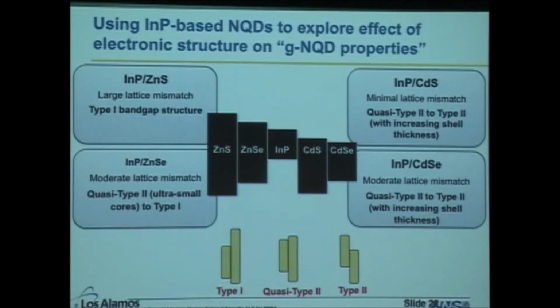And we like indium phosphide in general because if we tweak the composition of the shell from zinc sulfide to zinc selenide to cadmium sulfide, cadmium selenide, we can tune through, as a function of the core size but also the shell thickness, all 3 types of electronic structures: from type 1, where we have full confinement of the electron hole pair, through the quasi-type 2 stage, and occasionally in some of these systems to a fully type 2 scenario where we get full spatial separation between the carriers. So we are developing new syntheses. Prior to our work, really the zinc sulfide indium phosphide system was the only one known, maybe 1 paper on zinc selenide. And so all of this is a new material space, and pretty exciting, we think.